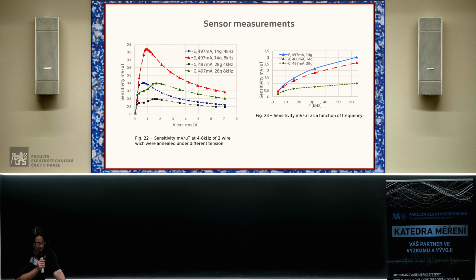So, here is a comparison of two sensors with two different types of cores. One core is annealed with a current of 497 milliamps, but the stress tension is 12 megapascal, which is a weight of 14 grams. And another type of wire has the same conditions, but the weight is twice higher. It's 24 megapascal, which is 28 grams.